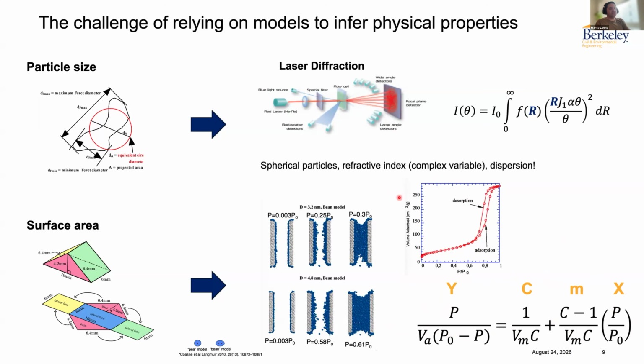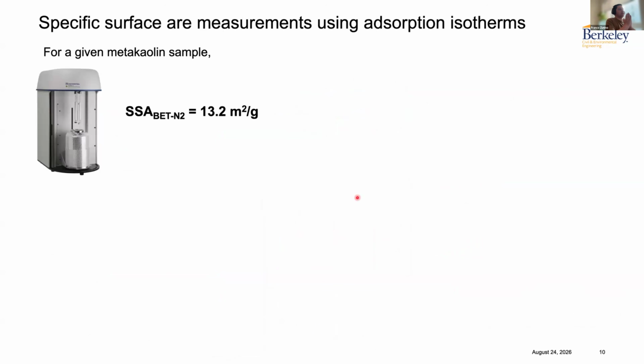However, there is a bunch of assumptions that are being taken in this model, particularly that there is no chemical interaction between the nitrogen, in this case, and the surface, and also that we have a monolayer coverage, and that's why we only use the lower part of the isotherm where we have a really linear behavior. However, the issues arise when we start trying to compare the measured surface area by BET with things like reactivity, and we see that in many cases there is no correlation. And I would like to highlight that with an example.